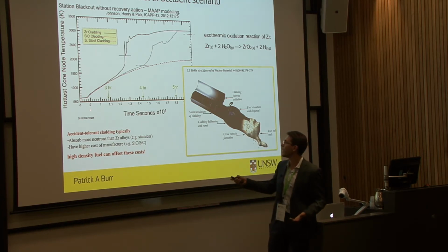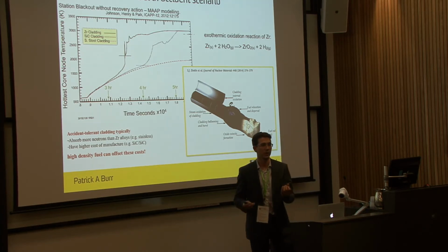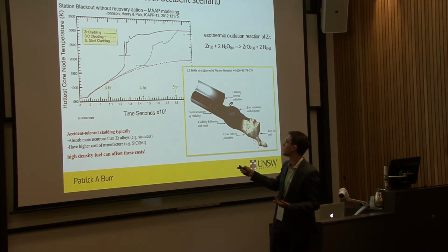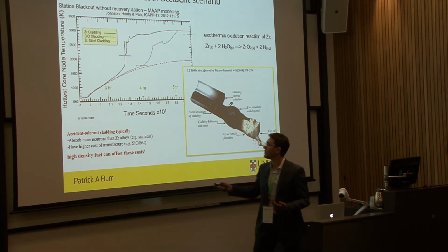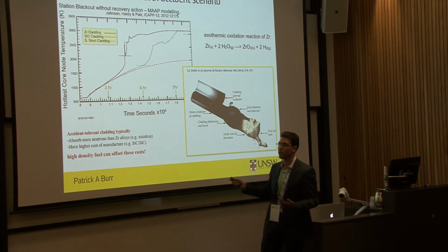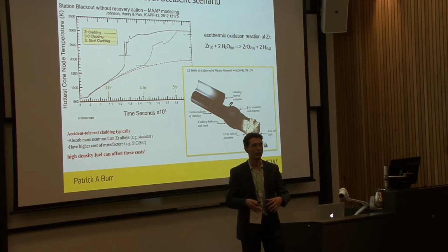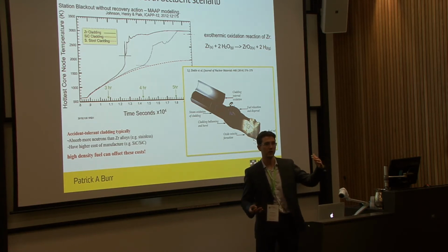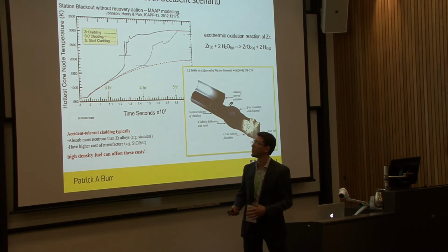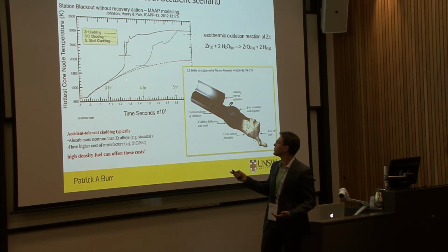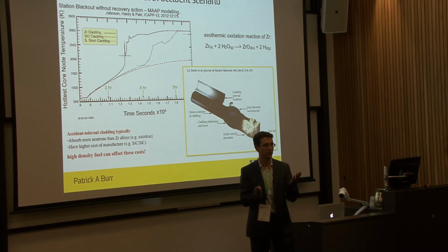Eventually, at about 2.5 hours, the hottest part of your core will start to dry out. The fuel pins won't be in contact with water anymore, and as that happens, they start to warm up quite rapidly. That should follow a nice parabolic line, because since your reactor is shut down, the amount of power generation should decrease with time from decay heat. And also the temperature difference between the cladding and the fuel should slowly get to an equilibrium.